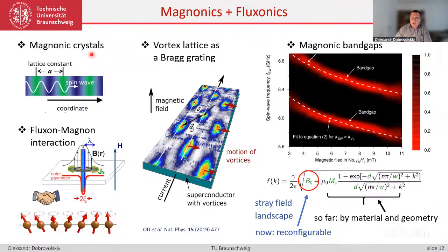In particular, if one has a modulation of a magnetic parameter, for the propagation of spin waves, this medium behaves as a magnonic crystal. What does it mean? If there is a match between the spin wave wavelength and the periodicity of the system, then spin waves will be scattered, and because of destructive interference, like with the Bragg grating for solids, it should lead to the appearance of forbidden frequency gaps and allowed bands. So basically, it's a formation of a Bloch-like band structure. For fluxons, the major parameter which is of interest to us is this modulation of the stray field at the vortex core. It's at maximum. And when we have many vortices in a superconducting film, we have then a landscape of stray field, which will be acting on the magnonic waveguide.